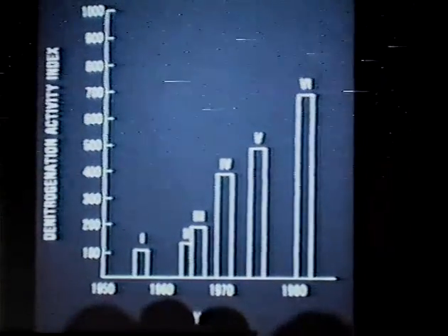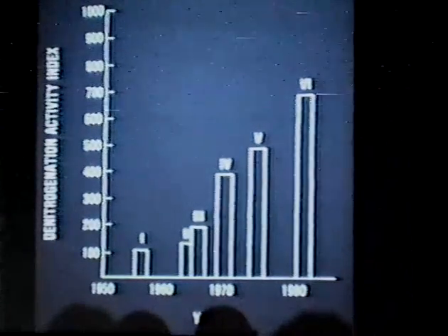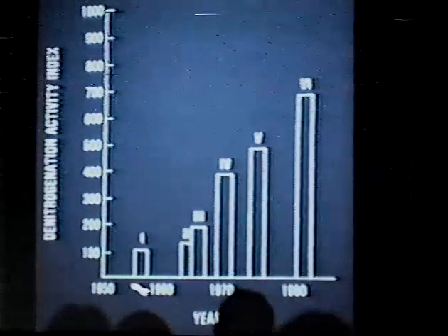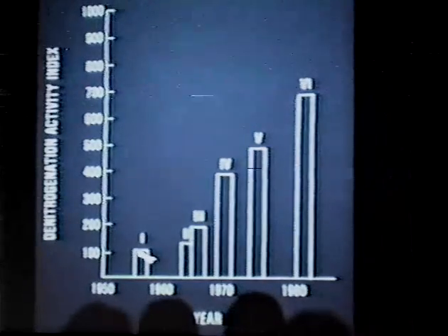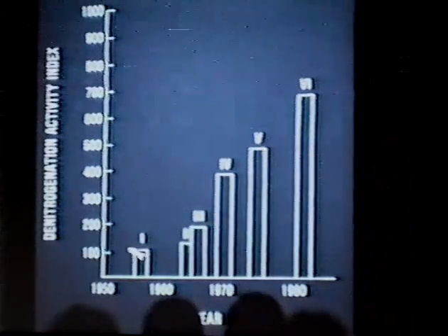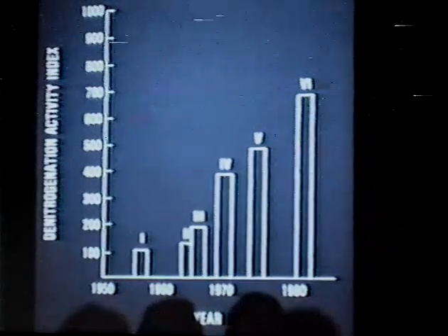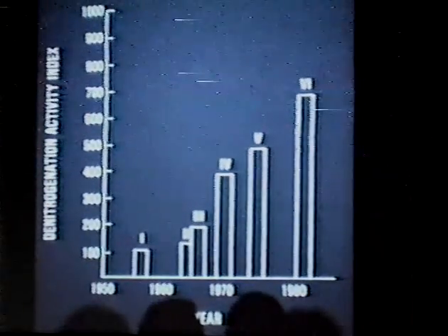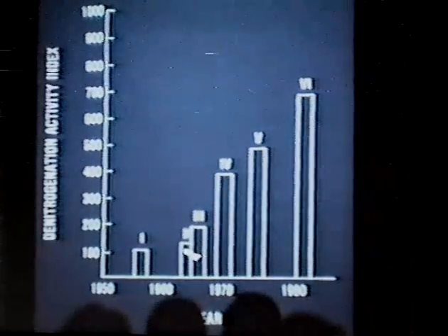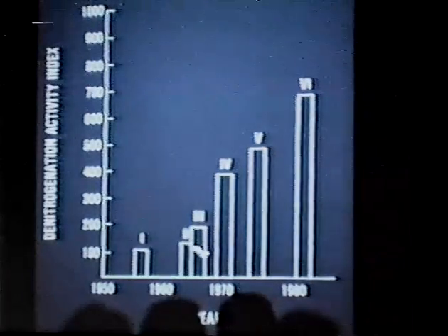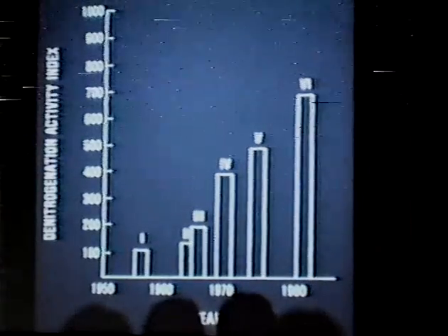Anyway, this slide shows you, taken off the map, a picture of progress for denitrogenation catalyst from the inception to the present time. This catalyst, which is arbitrarily given a 100 activity, was made back in the 50s, and it consisted of copelleting cobalt and molybdenum and aluminum, and calcining that. This stage 2 catalyst consisted of changing from cobalt to nickel. This stage 3 consisted of using extrusion technology to make the particles rather than copelleting.